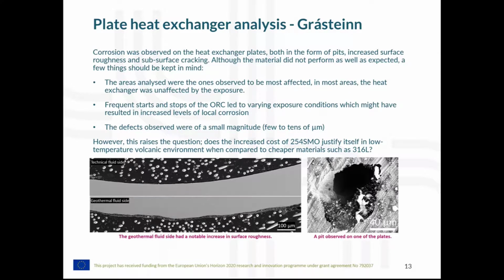But although we did see some pits and some surface roughness increase, what we should keep in mind is that the areas that we analyzed were the ones observed to be most affected, and in most areas of the plates and in most of the plates, we saw that the material was rather unaffected by the exposure. Another thing to keep in mind regarding the plates at Grásteinn is that we had in some cases some frequent starts and stops of the ORC and some potential atmospheric intrusion into the heat exchanger flow line, which can of course increase corrosion. And although we did observe increased roughness and pits, they are in small magnitude, a few to tens of micrometers.